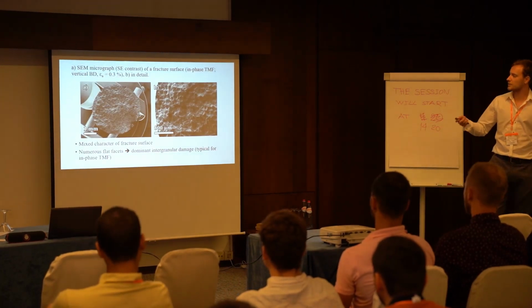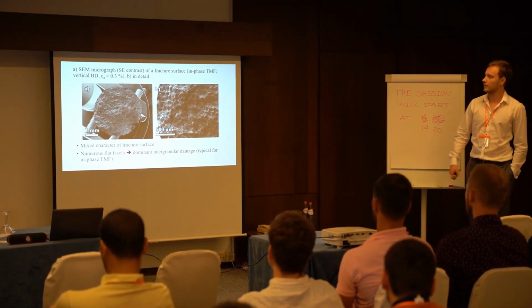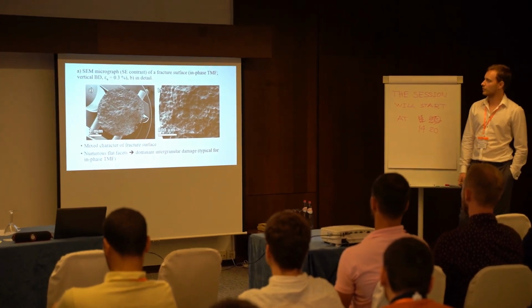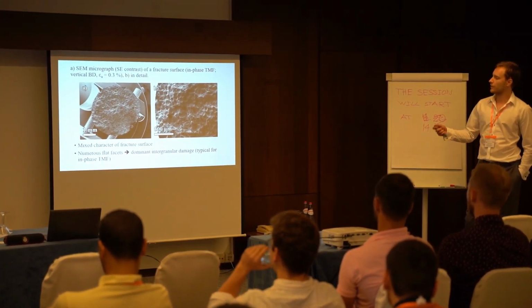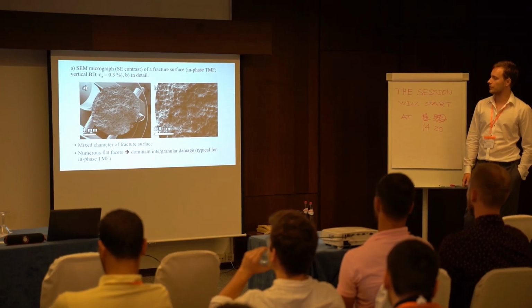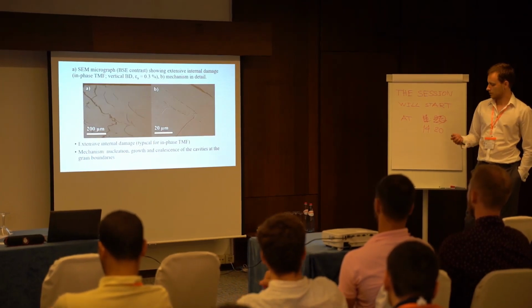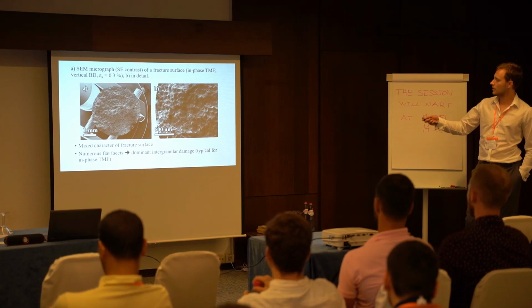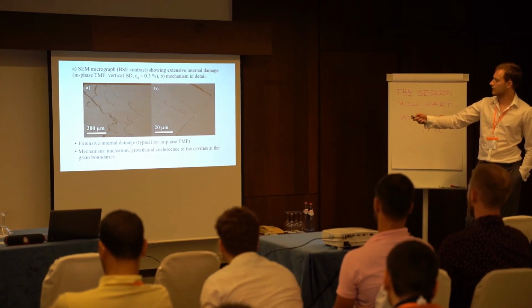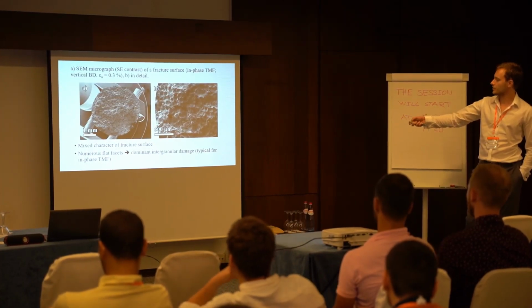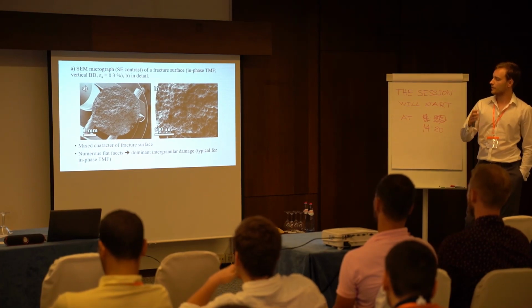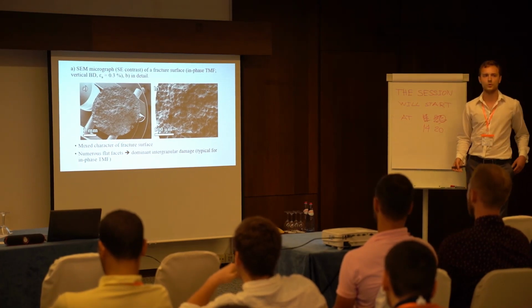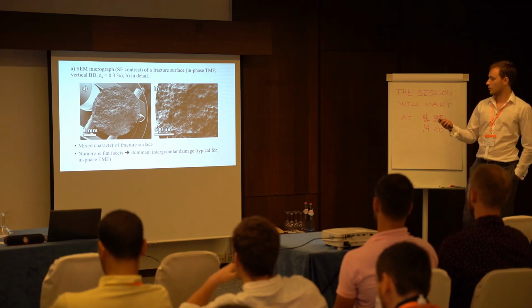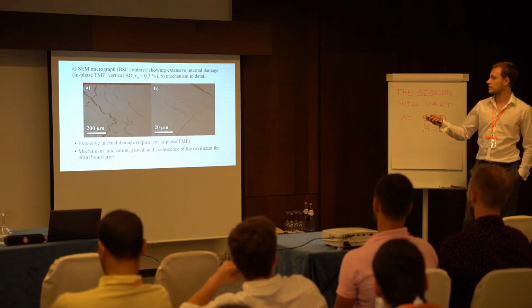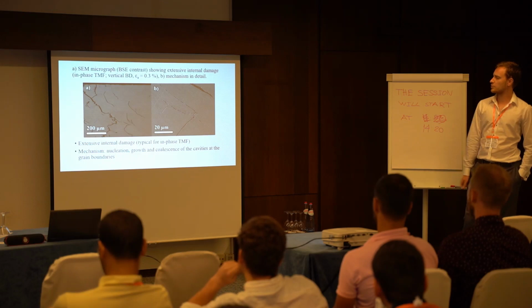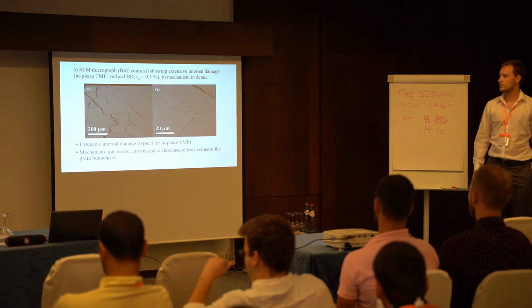Okay, so now let's see what the actual mechanisms are like. Yeah, so first let's take a look at in-phase tests. Here we have fracture surfaces which show numerous flat facets which are somewhat connected through small transgranular bridges. However, the damage character in general was mostly intergranular, which is kind of typical for in-phase tests. In these pictures, we see what the damage mechanism was like.